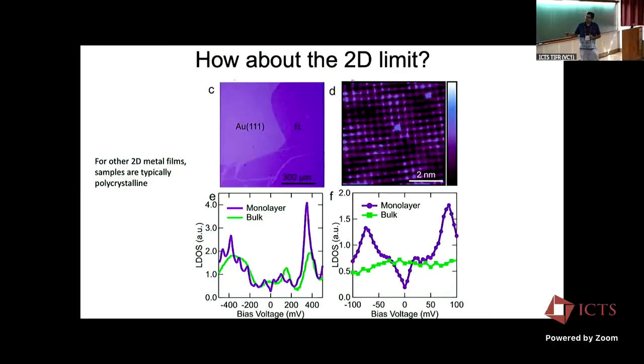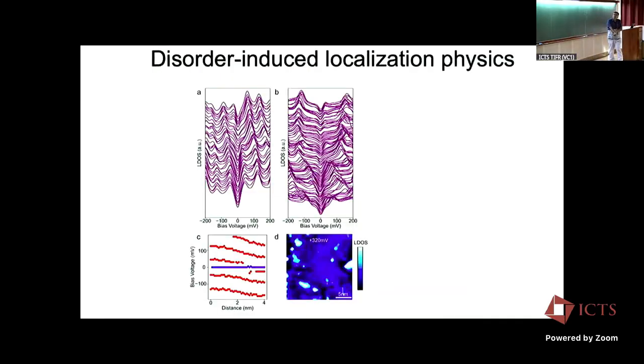If you measure the spectrum of the 2-dimensional film of this compound versus the bulk, you can immediately see that the spectrum looks completely different. It has all these peaks in the spectrum everywhere, as you might expect if you have localized states. You can go around in space and you can follow the local density of states everywhere in space.